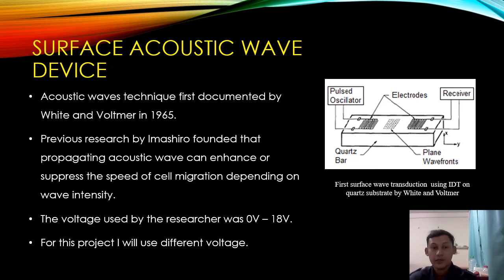Previous research by Imashiro found that a propagating acoustic wave can enhance or suppress the speed of cell migration depending on the wave intensity. Imashiro used voltage in the range of 0 volt to 18 volt, but for my project, I will use a different voltage that is more than 18 volt.